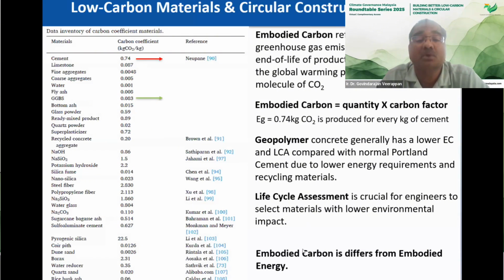I think Dr. Khairolden did mention a good effort they are putting into the calculator. But I just want to show these two figures to show what conventional cement actually produces. About 0.74 kg of CO2 is produced for every kg of cement. Compare that to GGBS, ground granulated blast furnace slag, a by-product of steel. It's only about 0.083. So you can see the difference. These are the materials you need to combine to have a sustainable, low carbon cement.